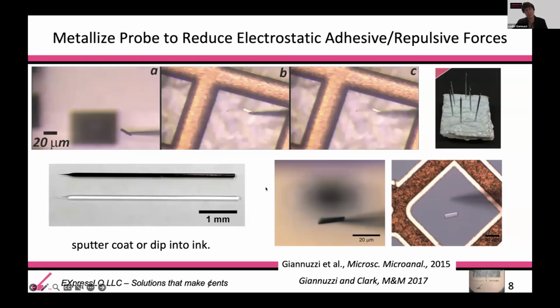So the glass tips will bend and deflect without breaking in most cases, and so you can fish around the trench for the specimen without having the tip break. And by either coating the tip with, for example, hobby ink or in a sputter coater, we can metallize the tips, and we found a lot of success doing that.